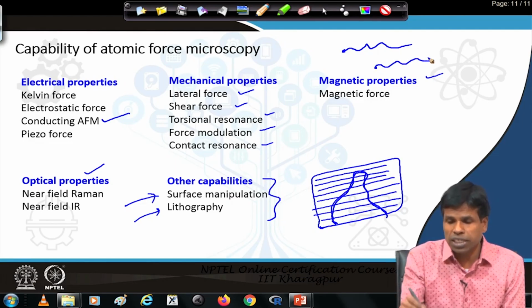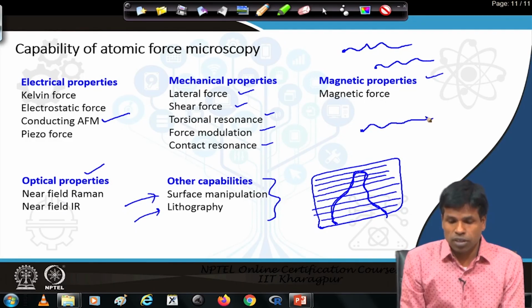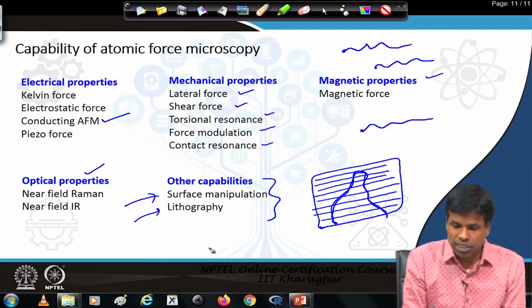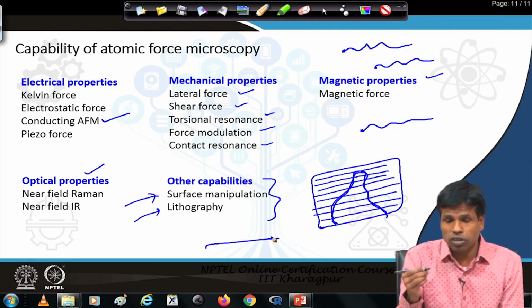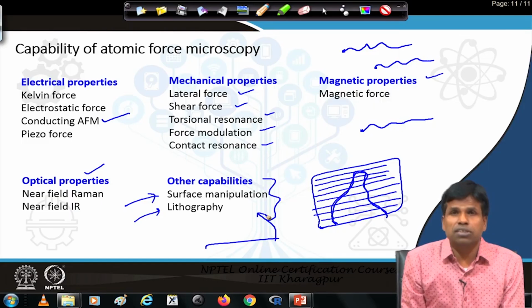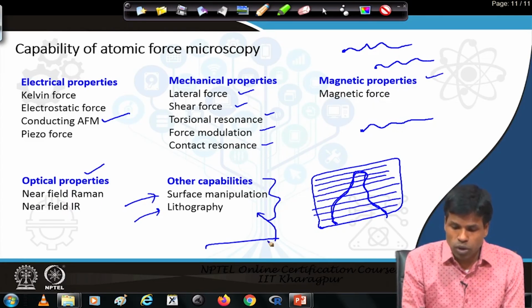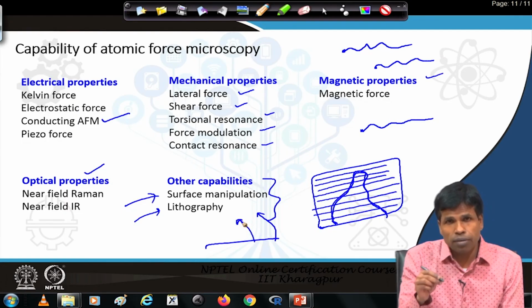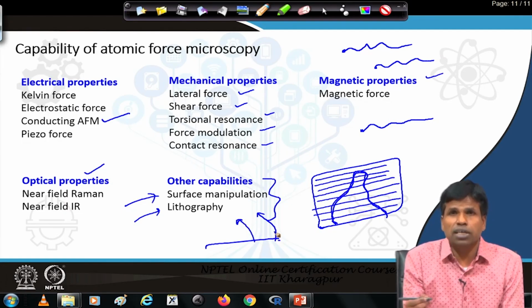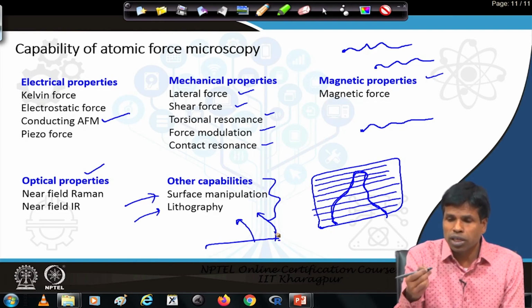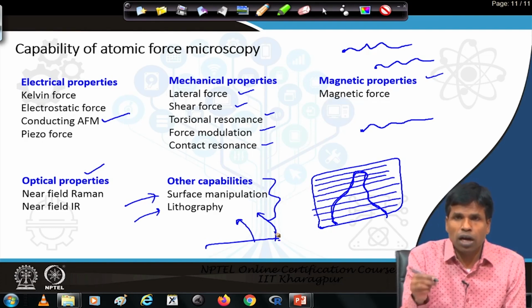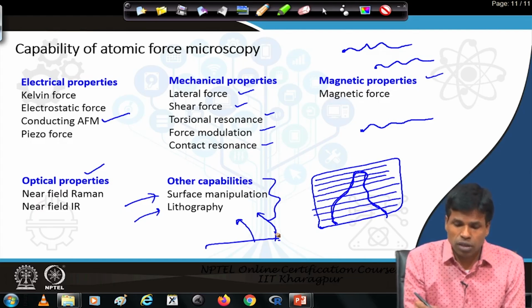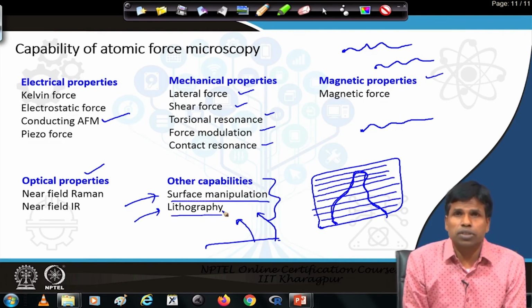If my tip is atomic, I can write on an atomic scale. Or if there is something on the surface, let us say a nanowire, I can use that tip to displace it to a different position, or I can bend the nanowire, let us say a straight carbon nanotube, using this probe. One can bend that carbon nanotube to the desired position or desired angle. So, this is nothing but surface manipulation or manipulation of the nanomaterials. All these kinds of things can be done by atomic force microscope.